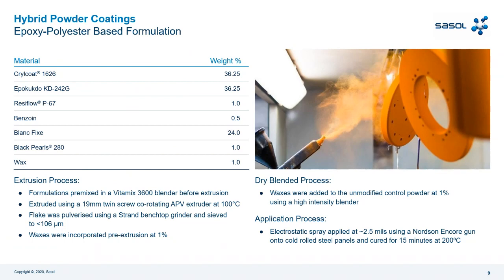In the dry blend process, waxes are added, as I mentioned before, at 1% also with a high intensity blender. I want to underline that the control that you will see in the results is without the 1% of wax. So our test underlines the different performance based on the wax, not based on other components. Application process: we use an electrostatic spray at 2.5 mils using an Nordson Encore gun. And we spray on the panels, and then we use an oven for 15 minutes at 200 degrees.